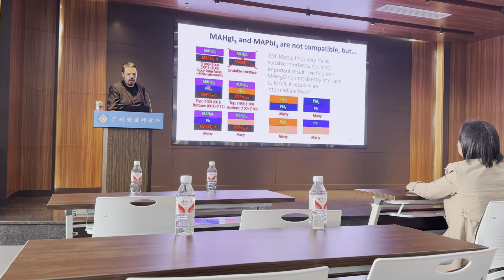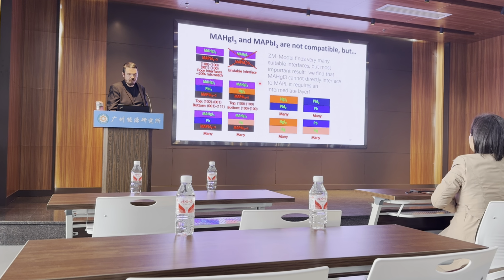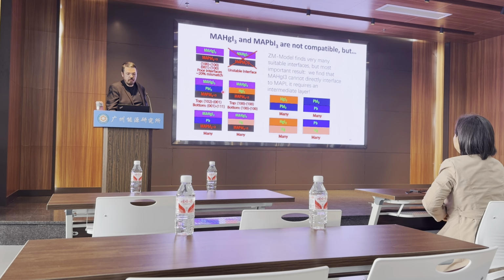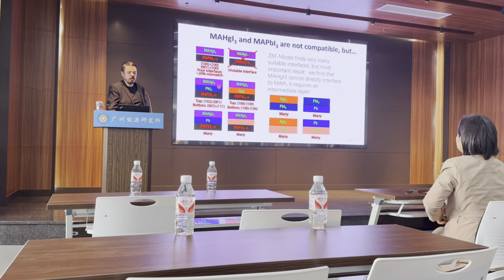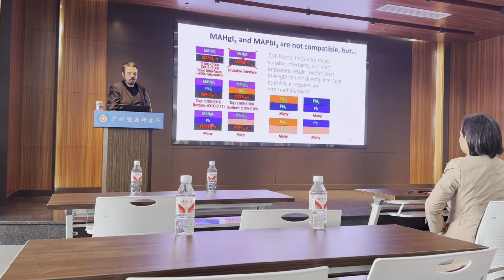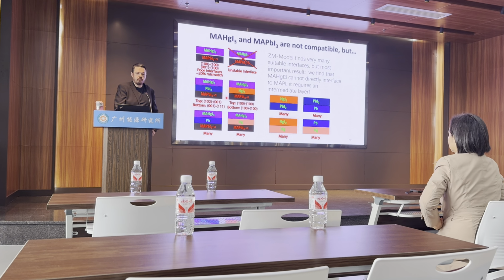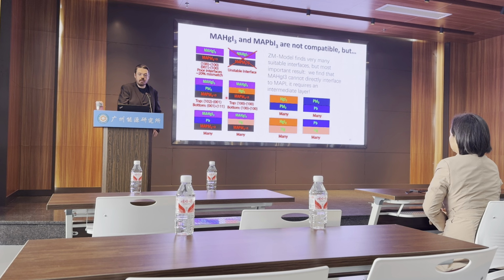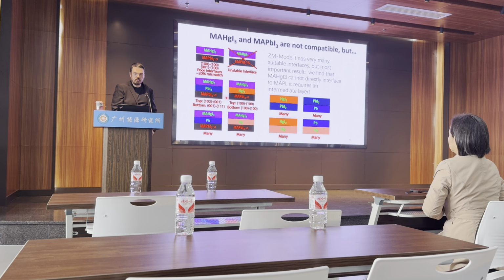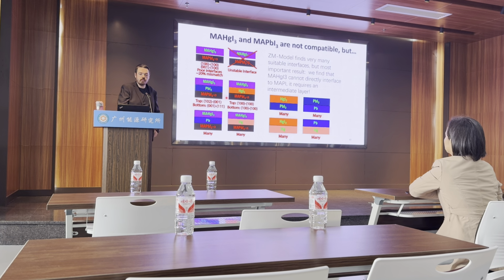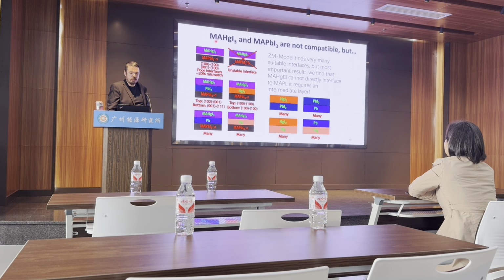So we have some kind of intermediate layer. And the intermediate layer might be PbI2, HgI2, Pb, Hg, etc. What we found basically is 20 megabytes of possible interfaces. These are all tables, so it's a huge amount of data. So all we did is exclude this possibility and just say that the possibilities are very, very many.